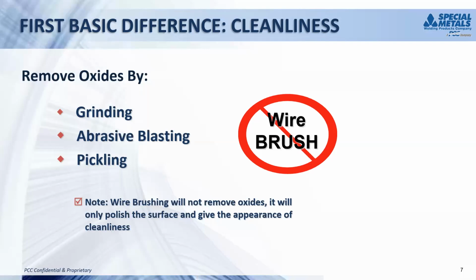And the best way to tell this for the welder is to look for a topographical difference. The oxide always floats on top of the puddle, and if it solidifies and attaches itself, there'll be a difference in the topography. There'll be a slight upstep when you get to the oxide. John?